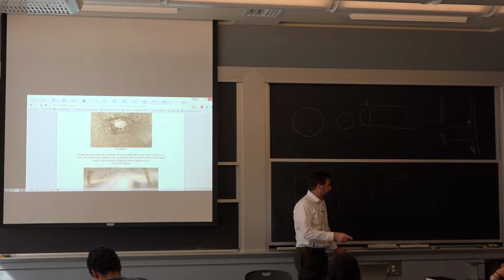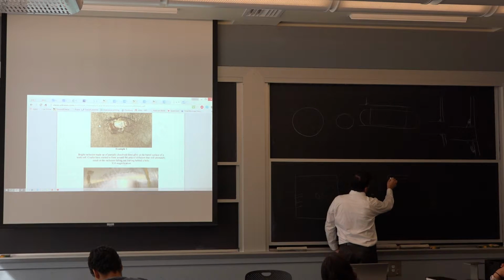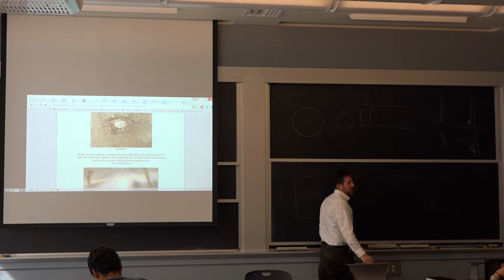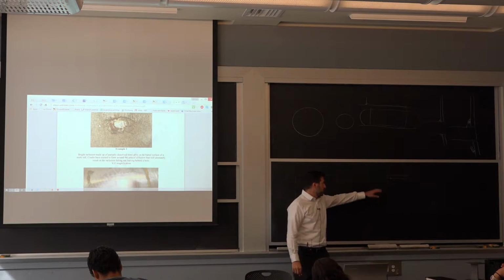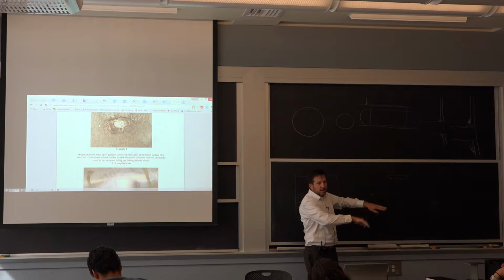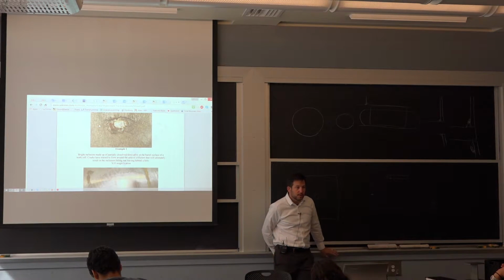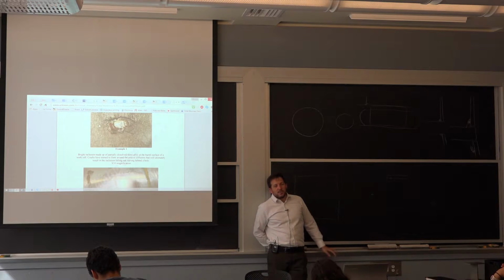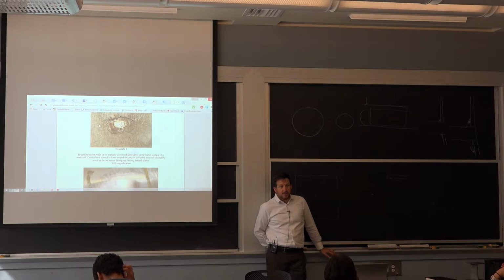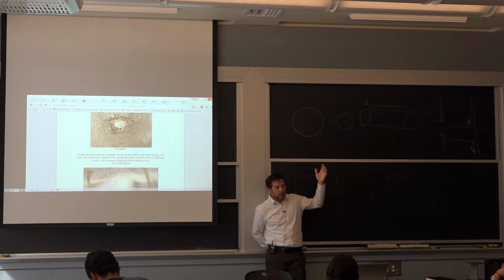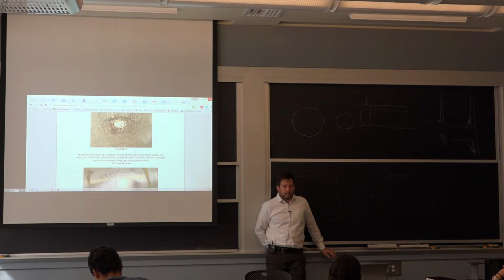And when we were getting a premature failure, a lot of times it's because we did have an inclusion that was very, very close to the surface. The leaf spring is essentially loading and bending, so you have the effect of high stresses there. And then the exercise was to look at the chemistry and figure out, does that come from our refractories that we use all the way up in the casting process, or does it come later in the rolling operation, as essentially chips or something from the metal that just got rolled into the product. So those are rolled-in inclusions.